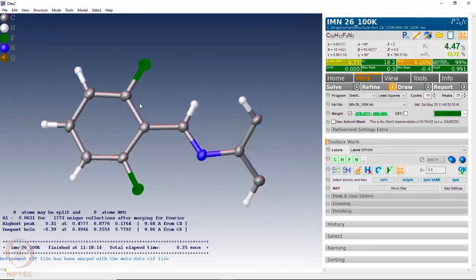This particular data is of very good quality, where these carbon hydrogen bonds are within the acceptable limits of bond length. The acceptable limit for carbon hydrogen bond length with an sp2 carbon, as in an aromatic system, should be between 0.9 to 1.1 angstrom. In case of poor quality data, it may so happen that the bond length increases to 1.2 angstrom, or the thermal parameter of the hydrogen becomes very large. So, the sphere on hydrogen may look very large.